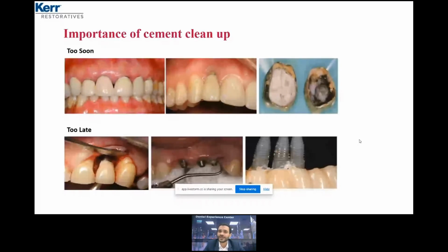Yes, you can remove it too late, after the cement reaches the well-defined structure. But in order to remove the excess too late, you need to apply high mechanical stresses, high mechanical forces. And we will have two options. The first option, I have succeeded to remove the excess, which is good. But because I applied high mechanical forces, high mechanical stresses on the crown, on the restoration, it can affect the bonding strength value of the restoration.